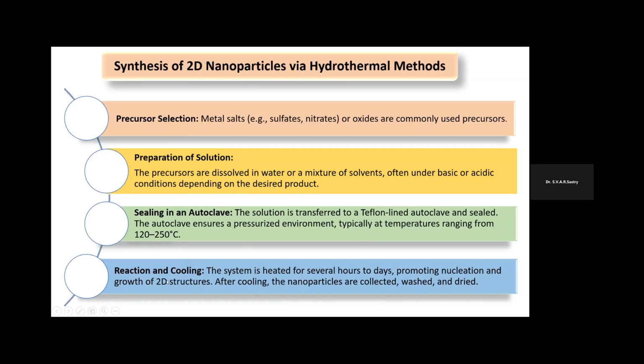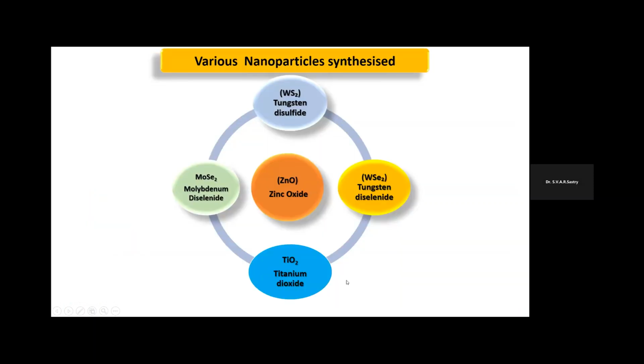Then the next one is reaction and cooling. The system is then heated for several hours or several days, depending on the type of nanoparticles to be made, promoting nucleation and the growth of two-dimensional nanoparticles in the autoclave. After cooling, the nanoparticles are collected, washed, and dried. So we have made these 5 different types of nanoparticles using this method, and all the 5 are used in making of nanolubricants. So the first one is titanium dioxide. Then we have molybdenum diselenide, then tungsten disulfide, tungsten diselenide, and zinc oxide. So all 5 have shown good performance in the engines.